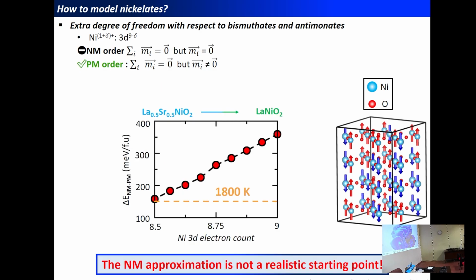Again, if we want to check the reliability of the non-magnetic approximation, we can compute the energy difference of various doped systems, from half doping to LaNiO2 system. And if we look at the energy difference between a real paramagnetic solution and the non-spin-polarized solution, we end up with a real paramagnetic solution which is much, much more stable than the non-spin-polarized solution. And the energy difference is around 150 meV, which does represent 1800 Kelvin. So it means that this non-magnetic cell, which is often used to compute the electron-phonon coupling and the superconducting properties in these transition metal oxide superconductors, is not a good starting point because these states would be stable at a much, much higher temperature. And therefore, we will use a paramagnetic representation of the nickel cation ordering.